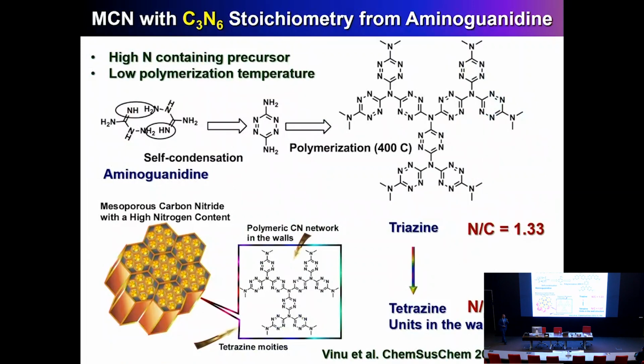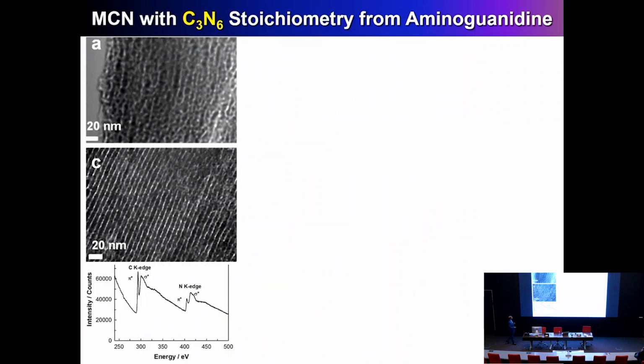So for C₃N₆, you have to have a completely different chemistry. So what we have done here is that instead of using the cyclic C₃ precursor, we use the non-cyclic C₃ precursor, that is the aminoguanidine. So the aminoguanidine undergoes self-condensation to get diaminotetrazine, and this undergoes polymerization to get the stable tetrazine-based polymer in the highly ordered nanoporous silica template. And when we remove the silica template, you could get carbon nitride with the C₃N₆, and that was again calculated by the CHN analysis. And these materials also have highly ordered porous structures.